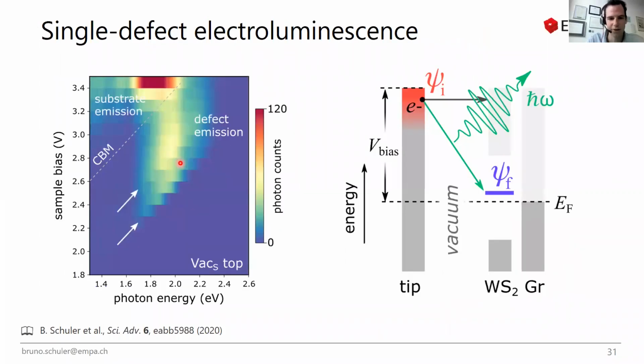It took us a while to understand what was really going on and what the mechanism is. There are a few competing models that try to describe how this STM luminescence works, and I think it's also specific to the type of system you're studying. In our system, the explanation we came up with is that most of the electrons, as in normal STM, will tunnel elastically, if we apply high bias, to the conduction band and then drain eventually to the graphene. But some of the electrons undergo an inelastic transition, from some state in the tip, which is a continuum of states because it's a metal, to our discrete defect state that lives isolated in the band gap.